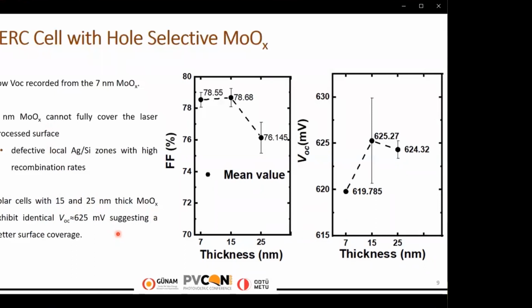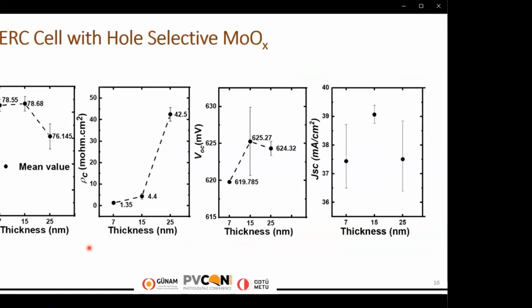While a clear correlation between molybdenum oxide thickness and different aspects of molybdenum oxides, such as contact resistivity affecting fill factor and surface coverage affecting mainly VOC and parasitic absorption in the infrared affecting JSC, PV characteristics are observed. These parameters are shown to be strongly interrelated and dependent on molybdenum oxide thickness.